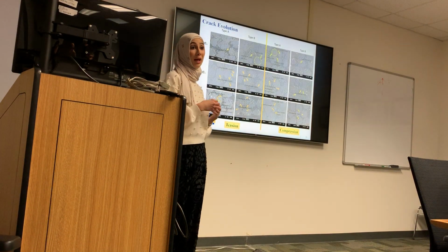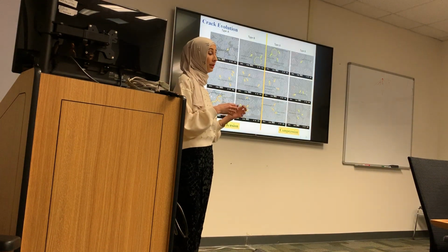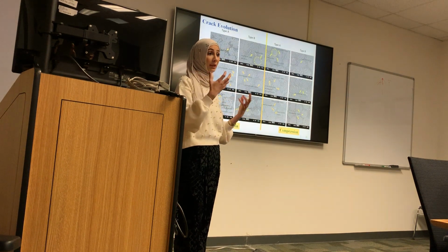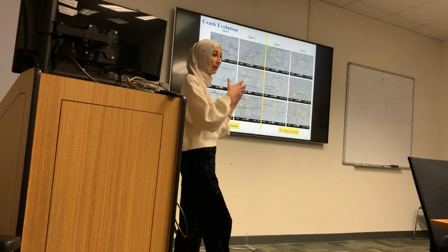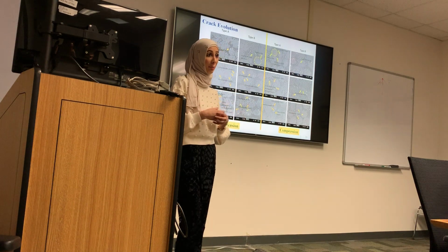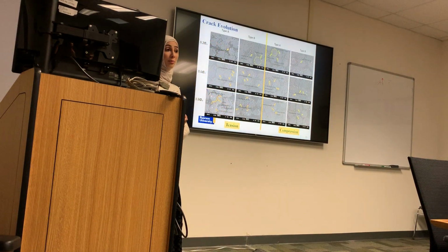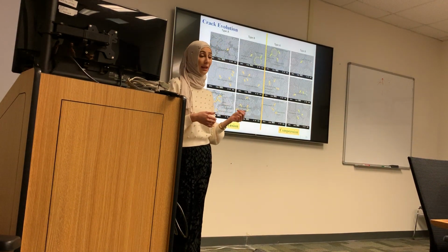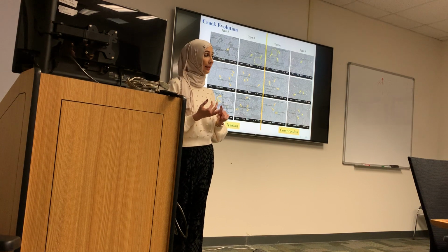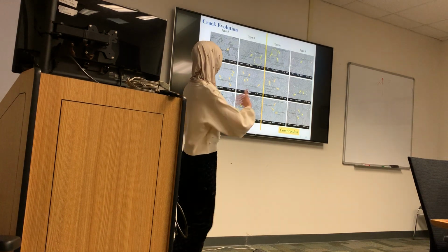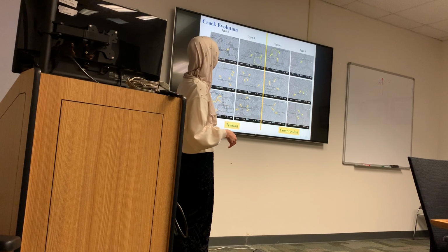We also study the crack evolution, so actually what is happening in the damage evolution. So we want to relate the profile to the actual damage happening in the material. What we did is monotonically loaded the specimen at 20%, 60%, and 80%. We see here on your right the compression, on the left the tension.